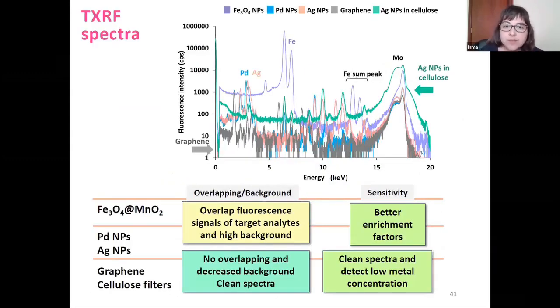In this slide, we can summarize the different spectra obtained for the nanoparticles studied here. We can see that, for example, in gray color, we have the background of graphene membranes, which is the lowest. Then we can see that for palladium nanoparticles, silver and cellulose, we have similar background, and we have to remark that the palladium and silver appear as small peaks when we use these nanoparticles, but they do not interfere in the analysis. However, the iron coming from the magnetite shows a high peak, so maybe it overlaps other elements.